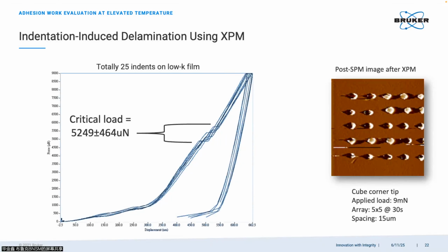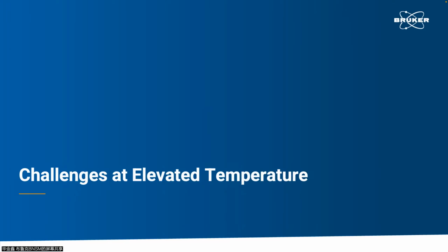From this viewpoint, you are able to induce a lot of interfacial debonding highly locally at a very high speed. So we can see there are 5 by 5, an array of indentation induced delamination, and you can pick up the critical load here. In this case, we know that these two small events are cohesion, so it is not what we are looking for, and this one is the adhesion event. So we can pick up the critical load here and have a statistical viewpoint. Because we have 25 critical loads in total, we have the average value together with the standard deviation. And this is the very first advantage of indentation induced delamination.